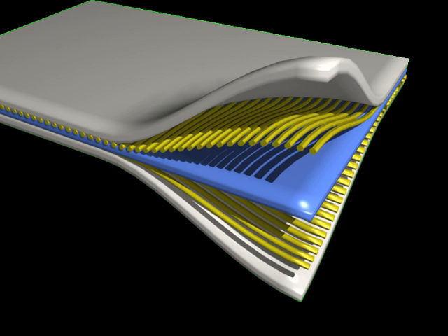Finally, for large values of theta near pi/2, transverse matrix failure is the most likely to occur, since the fibers no longer carry the majority of the load. Still, the tensile strength will be greater than for the purely perpendicular orientation, since the force perpendicular to the fibers will decrease by a factor of sin theta, and the area decreases by a factor of 1/sin theta, producing a composite tensile strength of sigma perp / sin^2 theta, where sigma perp is the tensile strength of the composite with fibers aligned perpendicular to the applied force.